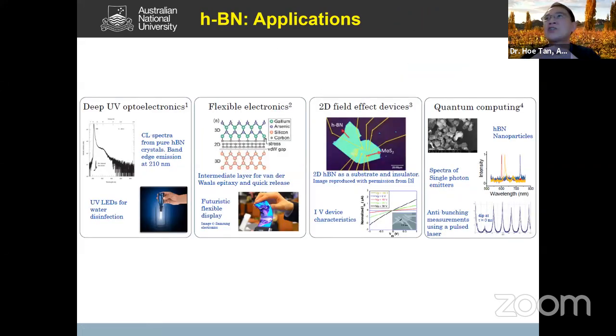So the way we grow this, before I start, HBN is already there. You can buy them off the shelf. Unfortunately, they come in very small size, typically a few millimeters in size. And in 2D materials, typically people peel it off with scotch tape. So if you peel it off, you're lucky to be able to get, say, a few hundred microns by a few hundred microns.